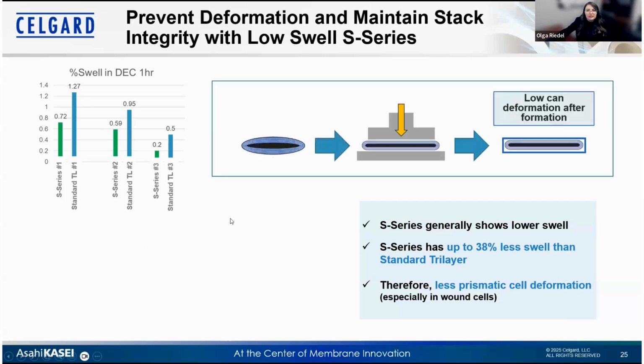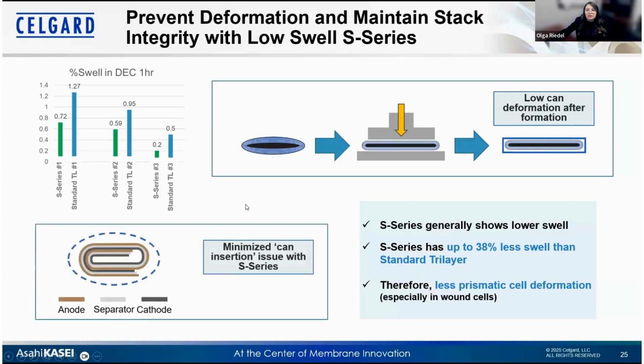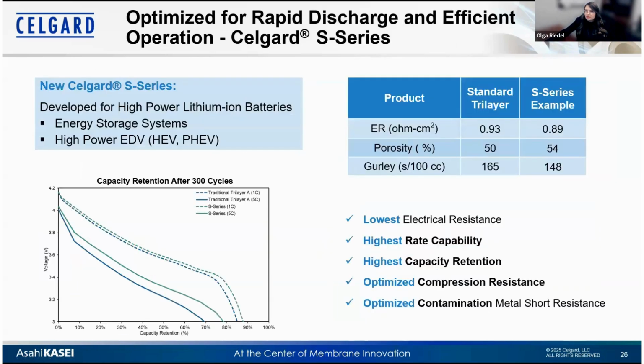Therefore, we can observe less can deformation, especially after formation in prismatic cells. But additionally, the low swell S series also has a low rebound. This helps to facilitate the can insertion of the jelly roll into the hard case prismatic can, and the same is valid for cylindrical cans. As earlier mentioned, the improved structure also allows for high power performance due to increased porosity, as you can see in this table, but also decreased internal resistance and decreased air permeability. This makes S-series a unique fit, especially in ESS systems using prismatic or cylindrical cells.